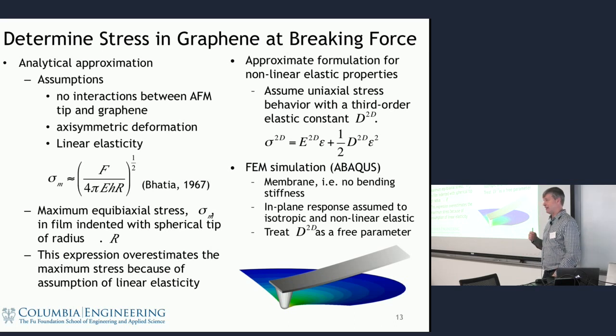Years ago, we were growing nanotubes and characterizing their chirality. I was working with Rod Ruoff to try to pull on these things and break them. And much to Rod's chagrin, we got some data, but we never managed to verify the theoretical predictions. That's because in a one-dimensional carbon nanotube, you always have to clamp, and you always have some stress concentration or some imperfection at the clamp, and they always broke at the clamp. So we got up to about 5% strain, and then we would always break at the clamping point.